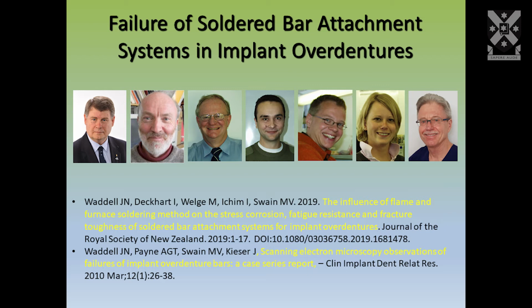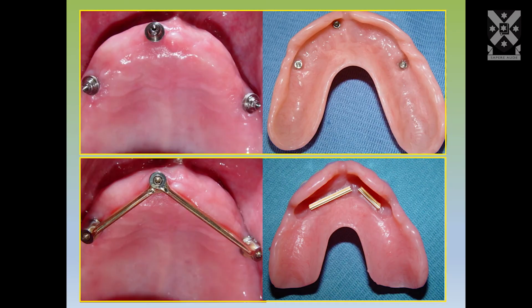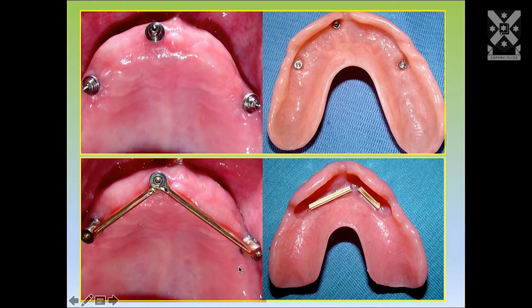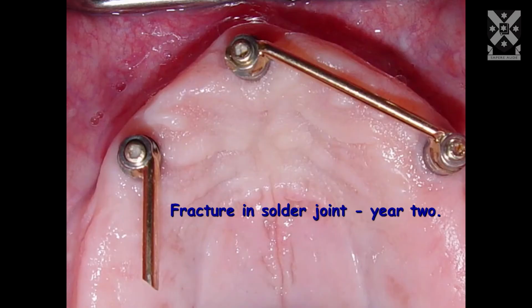And what was happening at the time is we were running clinical trials on attachments to help stabilize these complete dentures. In some cases we had ball attachments like this, and in others we had bars, and they were looking to see which were the most effective. But the problem was that some of these bars were failing at the solder joint after 1 or 2 years, and their lifespan should have been 10 to 12 years. And why were they failing?